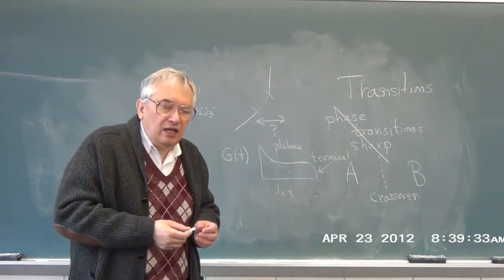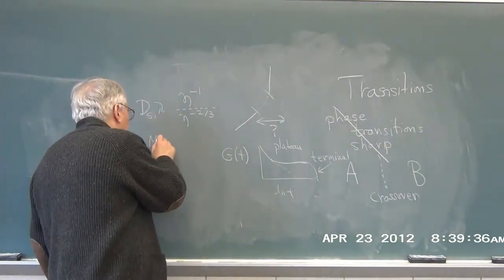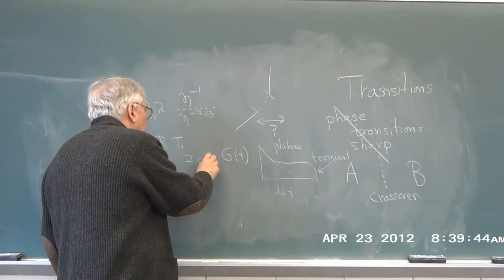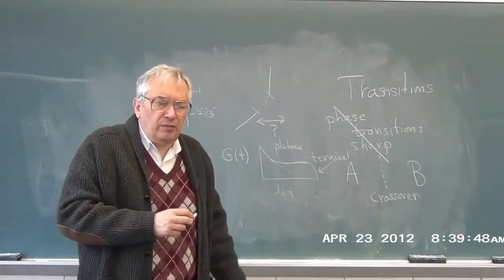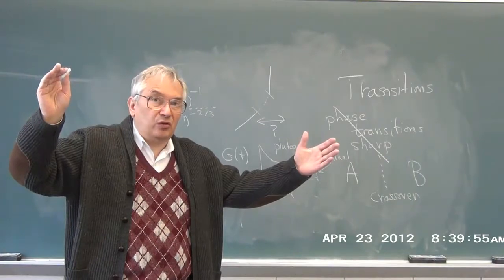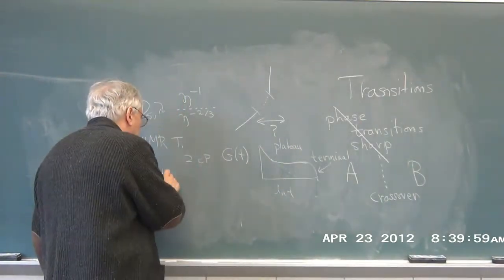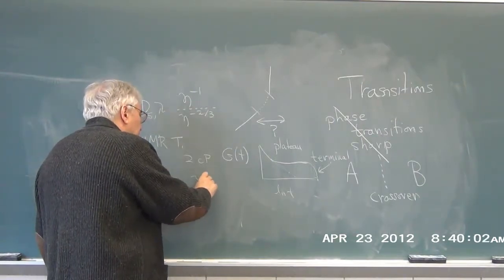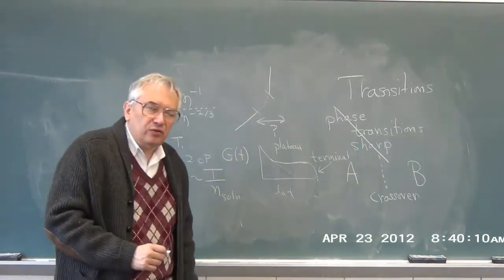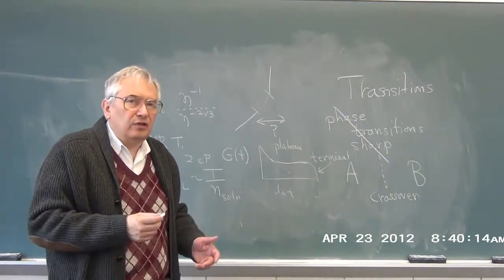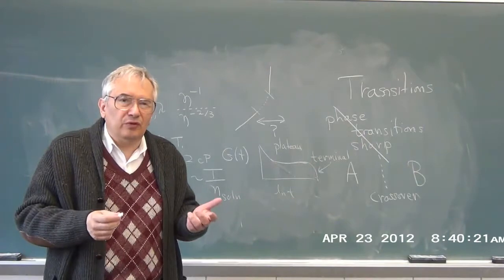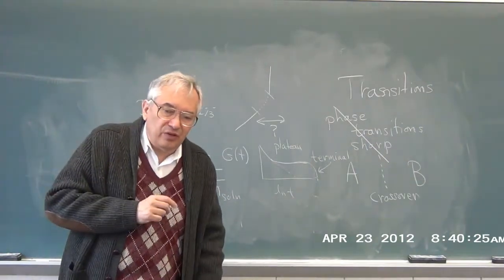You can also look at NMR T1 times for polymers. I didn't go into it in any detail in the lecture, but there is something interesting near about maybe 2 centipoise. Okay, on the other hand, if you look at polystyrene spheres, which are hundreds of angstroms across, in water glycerol, D of the polystyrene latex spheres goes as T over eta of the solution over at least 3 orders of magnitude. You can take that out to pure glycerol or nearly pure glycerol. You can go over a wide range of temperatures, and this is what you see. Eventually, if you supercool the glycerol, something else happens.